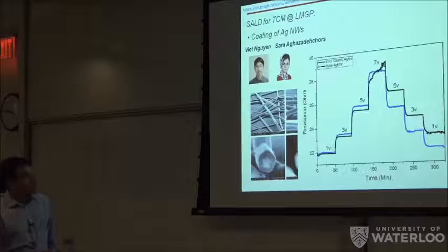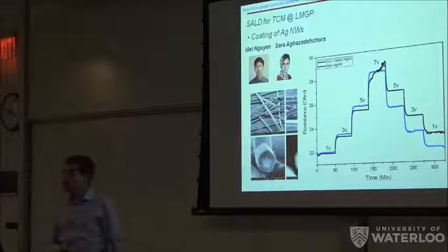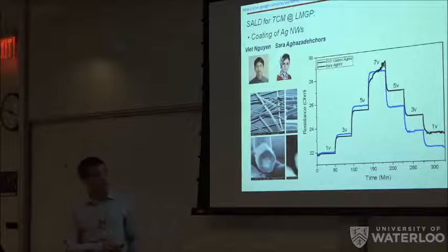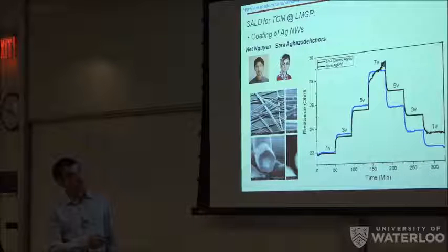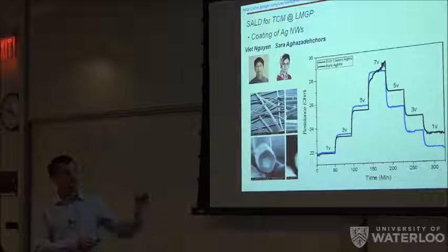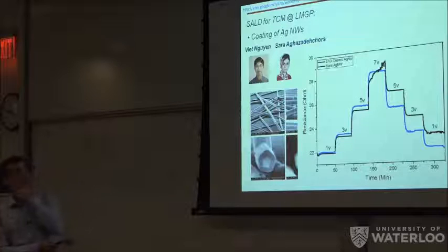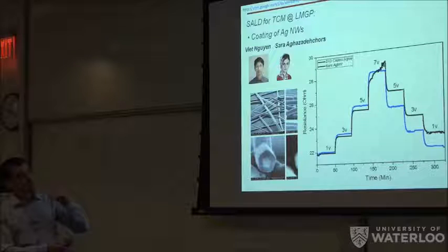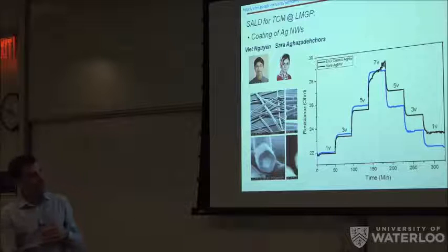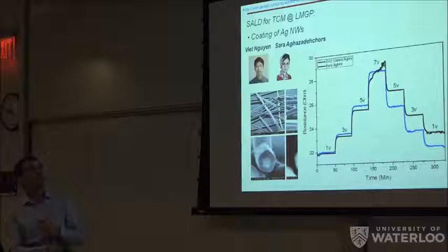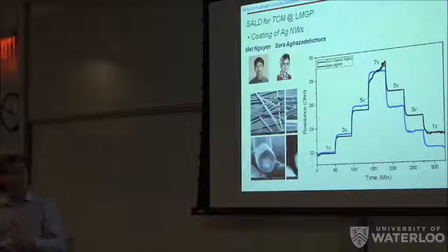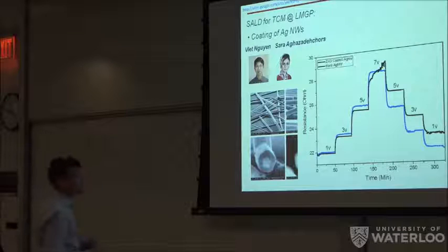And then you can see that, after applying this oxide coating, the potential becomes much more stable. And in this case, for instance, when we reach 7 volts, if the nanowires are not protected, the network starts failing. And when you go back to 5 volts, the voltage is much higher than it should be. While when you have them coated with zinc oxide, you recover pretty much the same, even lower resistance, because the junctions have been improved, so you have less resistance, and the whole device is stable.